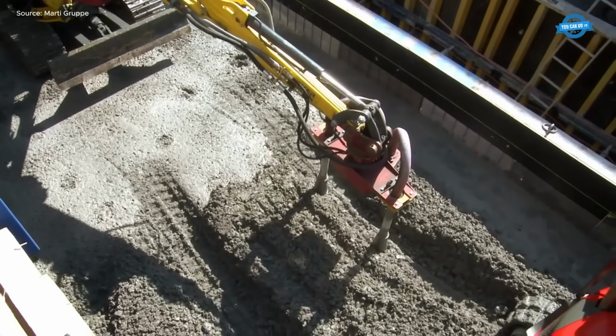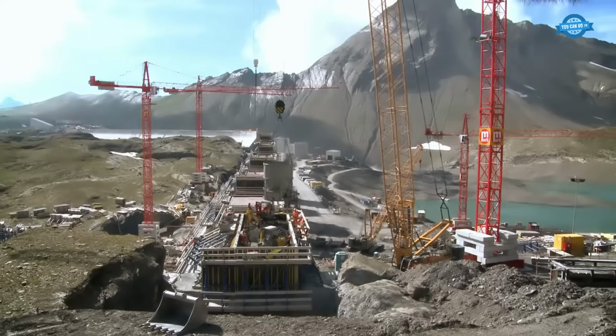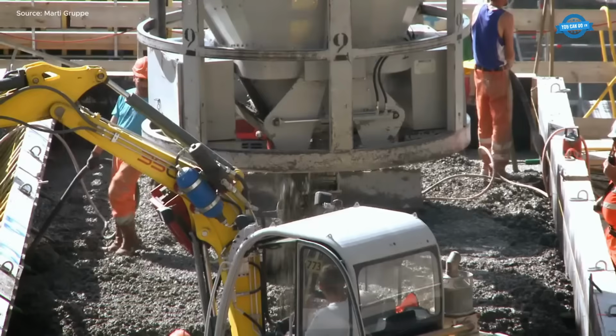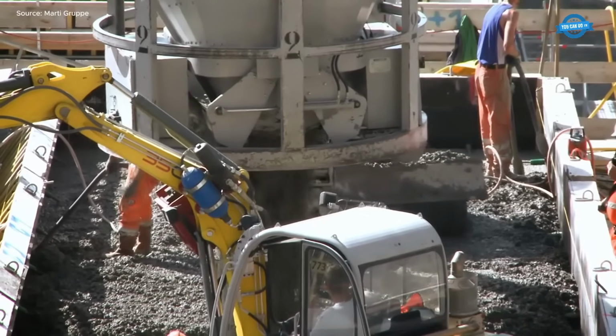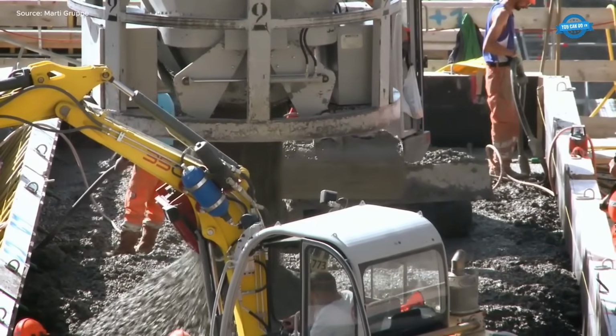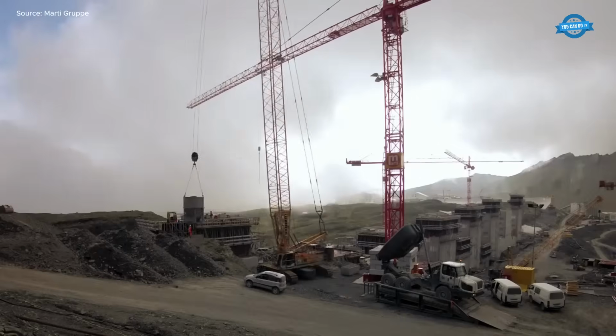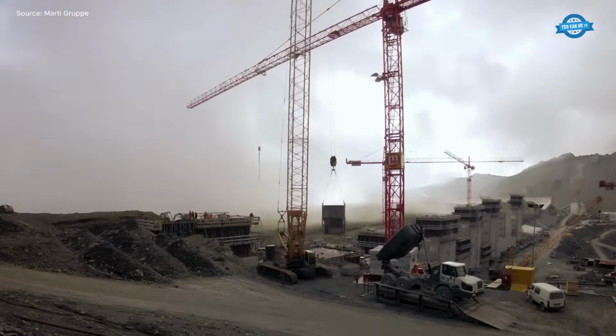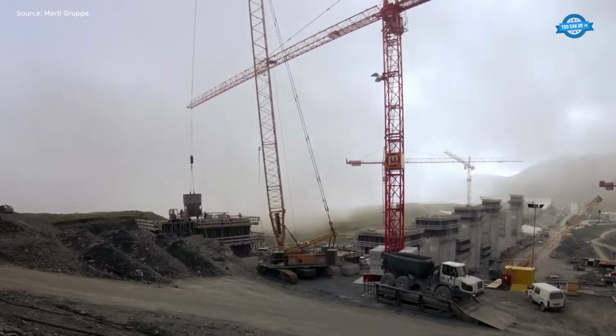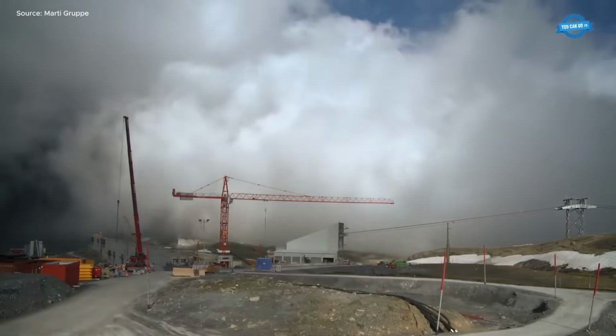Concrete was poured in layers of 50 centimeters, which had to be vibrated and compacted quickly before the next layer was applied, typically within 2 hours. The pouring of one block stage could last up to 12 hours. Surfaces were roughened with high-pressure water jets to ensure proper bonding with subsequent stages.